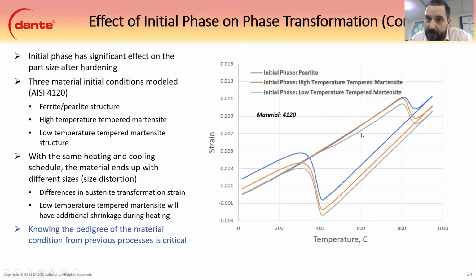You have definitely a volume shrinkage. And then it changes where your austenite is. And they all end up in different places here. Once you cool them down, we all go to martensite, and we all come back here, and it's all in a different end strain. And that's really important for the DANTE models.